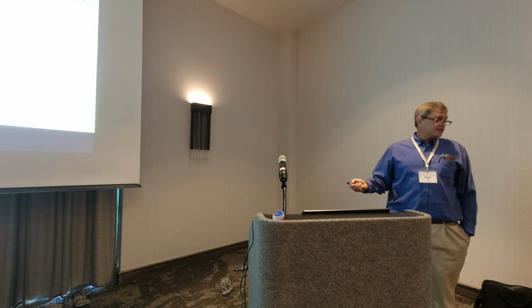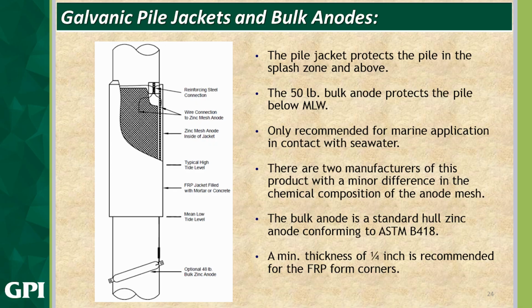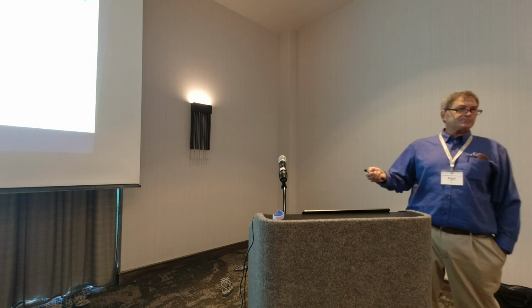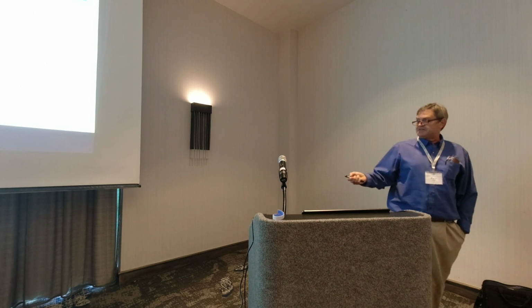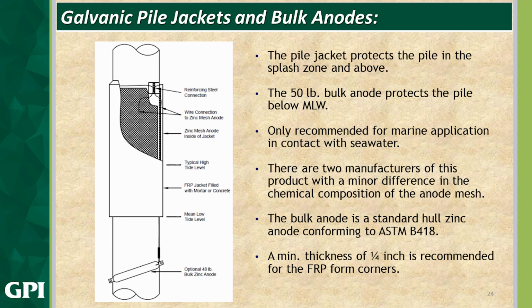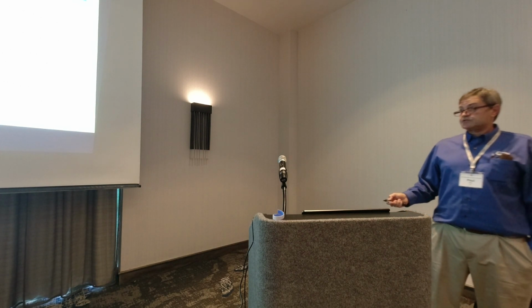This is only recommended for application in contact with seawater. There are two manufacturers of the product with a minor difference in chemical composition. The anode mesh... I'm kind of mixing up zinc and titanium. This slide is supposed to be specific to just galvanic. So when it comes down here, the bulk anode is a standard zinc anode conforming to B418. That's the zinc for the galvanic zinc mesh used for galvanic cathodic protection. A minimum thickness of 1/4 inch is recommended for the FRP form corners.